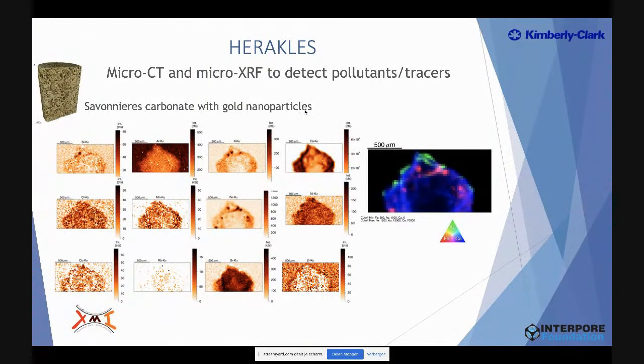So here is an example of our Savonnières limestone where we added some gold particles, and based on the micro XRF, we could see that in green is where the gold particles are present in our rock. You can also see that the resolution is not as high as with normal CT, but it can get small amounts of material lighting up very easily. In this case, our gold nanoparticles had around 60 nanometer diameter.